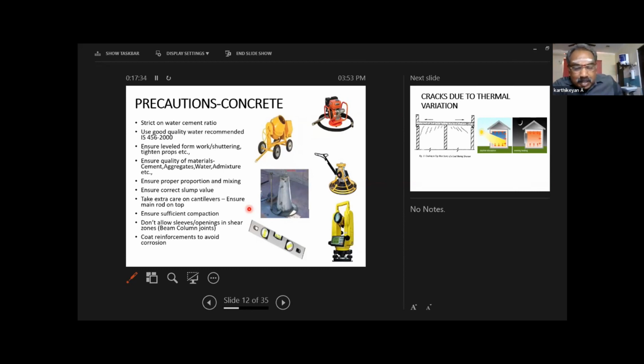Ensure sufficient compaction. You may use good material, but good methodology is important. So in case of concrete, use proper compactors, vibrators. Then only you can ensure good concrete. Otherwise, porous concrete may create cracking. Don't allow sleeves or openings in shear zones. Mostly in beam column joints, people make holes for sleeves for AC ducts, pipelines or plumbing lines. Beam column joints are high shear zones. In these high shear zones, if you make an opening, there is definitely not only a chance of cracking, but also collapse.